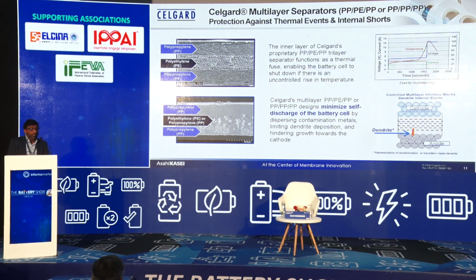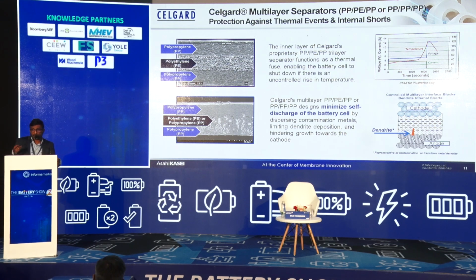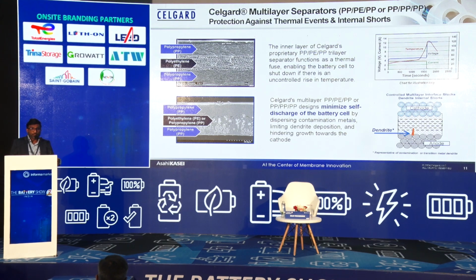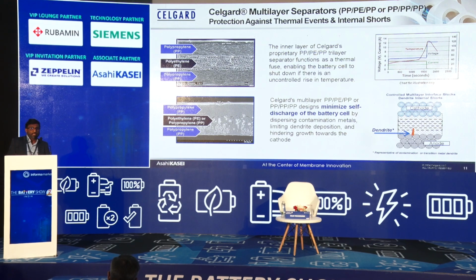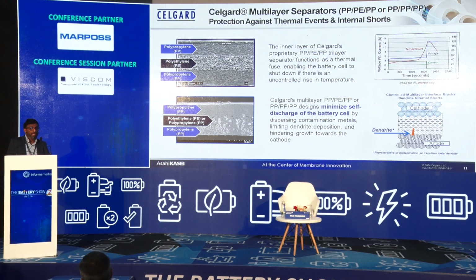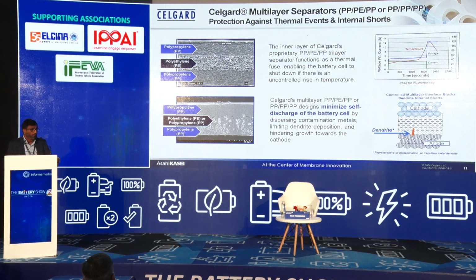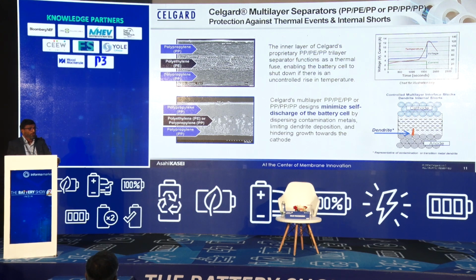The advantage of the tri-layer separators, as we call them, is that the polyethylene membrane melts at a lower temperature, so it stops the migration of ions from the anode to the cathode. It acts as a fuse, so that in case of a thermal event, it can totally isolate the anode and cathode and protect against fires happening inside the cells. That is one advantage. The second advantage is that, since it has multiple layers, the migration of dendrites can be minimized quite a lot, because the dendrite has to pass through multiple layers. These are the 2 major advantages of multi-layer separators. It is possible only with dry separators, and it cannot be done with wet separators.